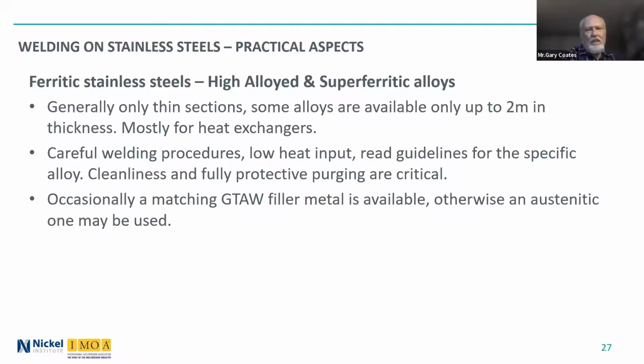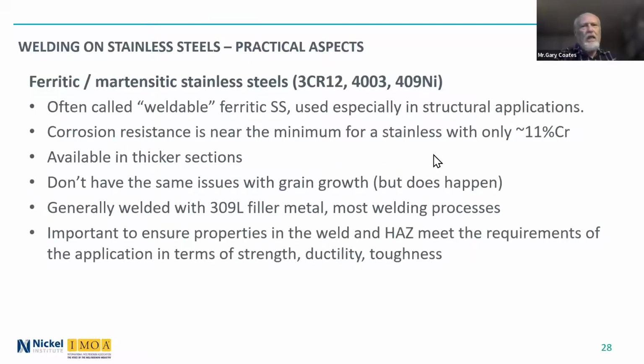And it's used mostly as heat exchanger tubes, these alloys. Very careful welding procedures, very low heat input. Read your guidelines for the specific alloy. Cleanliness and a fully protective purging are critical. Occasionally, a matching gas tungsten arc filler metal is available. Otherwise, an austenitic one may be used of the appropriate corrosion resistance. These are all used in corrosion applications.